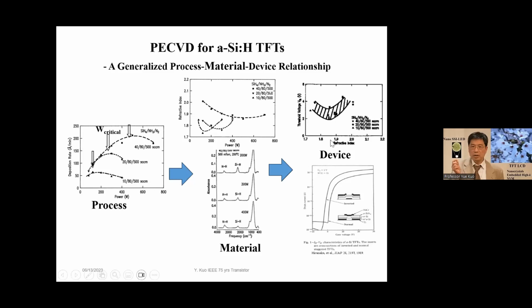So this gives a very simple guideline. So from the process, we can tailor towards the optimum device performance. This relationship has been widely used in the industry in developing a new process. And the reason the deposition rate condition can affect film quality and device performance is because plasma CVD is a unique process. Plasma CVD deposits film because of radical formation during dissociation of silane, ammonia, N2.